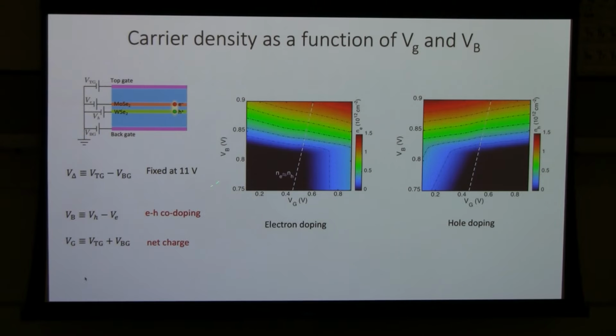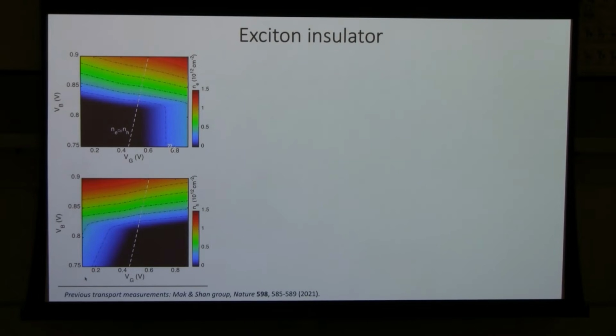But when the bias voltage is large enough, what you can see is that you can create electron doping over here and hole doping over here. So basically you can create electron and hole doping at the same time. So with this kind of density mapping, we can take a closer look and see how the electron and hole density change correlatedly based on the different control knobs.